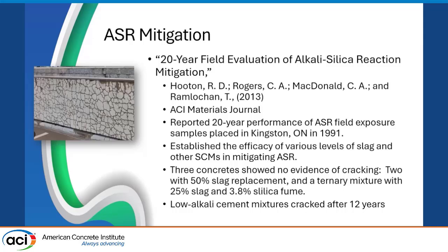ASR mitigation, another very large and important area of research. This particular study is kind of a culmination, a 20-year field evaluation of ASR mitigation. And this was in the ACI Materials Journal, reported 20-year performance of ASR field exposure samples placed in 1991. And among the many results and conclusions of the study, he found that there were actually 3 concretes that showed no evidence whatsoever of cracking with a deleterious aggregate. 2 were with 50% slag replacement, and a ternary mixture with 25% slag and 3.8% silica fume.